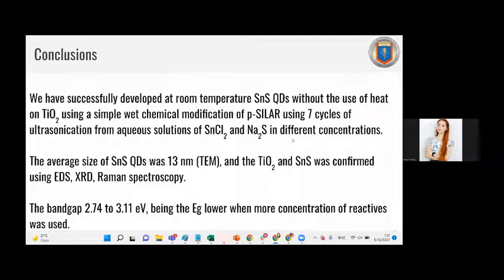And as a general summary, one way to revolutionize solar energy production is to reduce the complexity of the manufacturing process, and the possibility to apply this kind of paste in any shape and any surface. And in this work, we used the pseudo-SILAR technique to develop quantum dots on titanium dioxide, and we successfully developed quantum dots on titanium dioxide using simple wet chemical modification of pseudo-SILAR using 7 cycles of ultrasonic bath in aqueous solution of tin chloride and sodium sulfide.